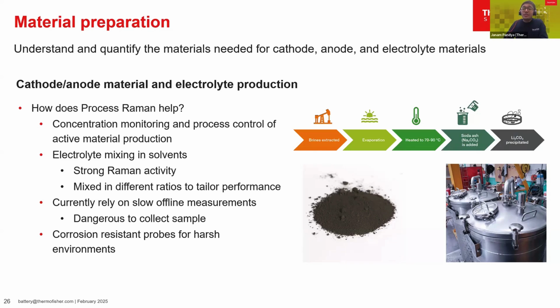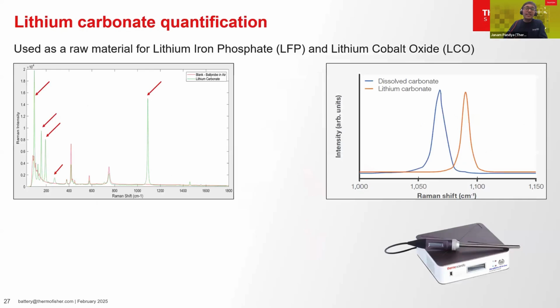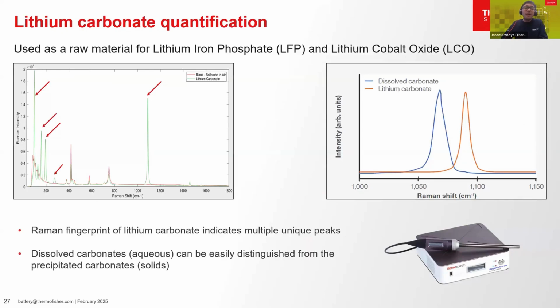The next slide shows the Raman signature of an example cathode material. The spectra on the left-hand side of the screen shows the Raman fingerprint of lithium carbonate, which is used as a raw material in LFP and LCO manufacturing processes. During the synthesis process of lithium carbonate, the lithium carbonate can be differentiated from dissolved carbonates and can be quantified due to the distinct peak as shown by the orange spectra in the figure on the right-hand side. Moving to the next slide.